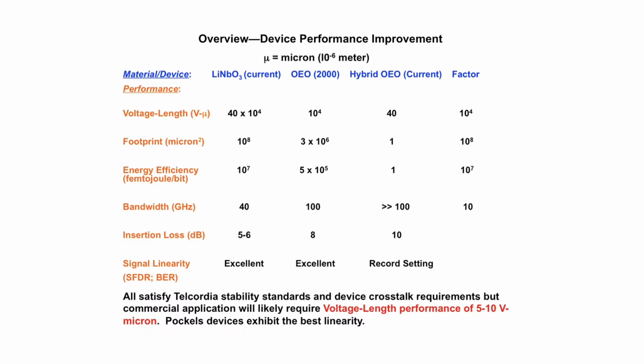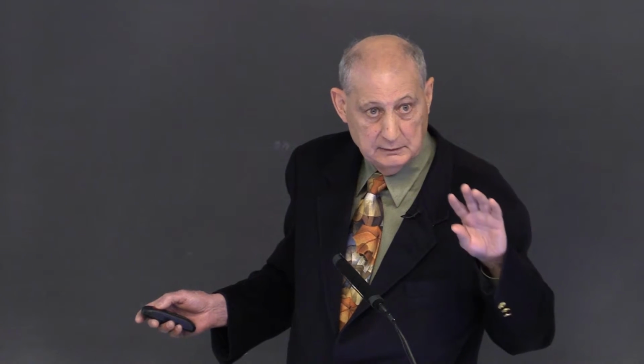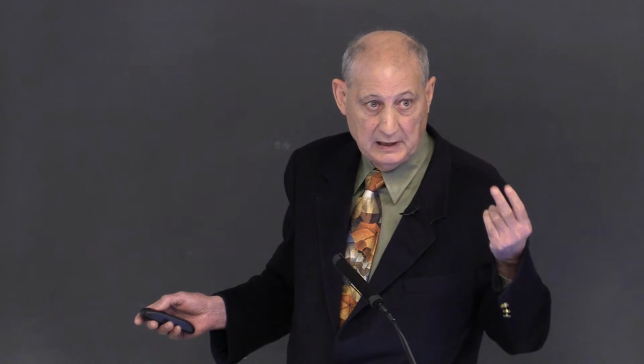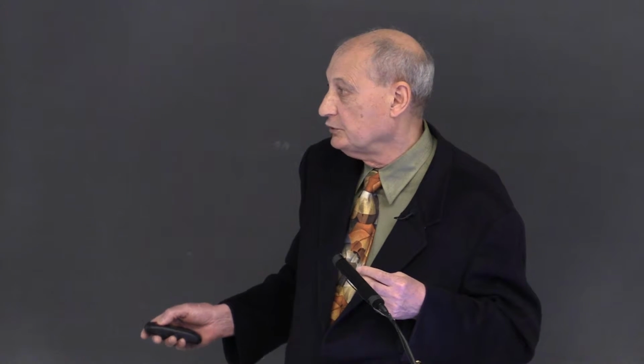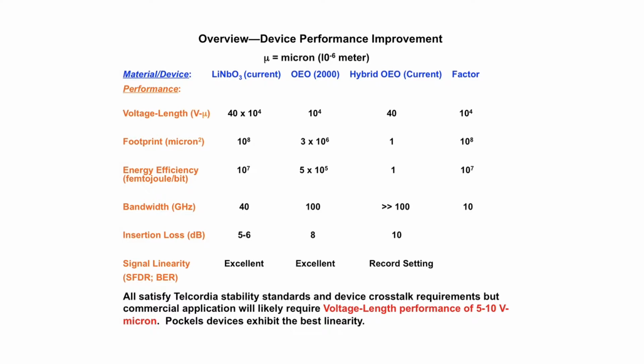Now, all the technologies shown here are Pockels effect modulation. That means when you apply the voltage, the only thing you do is produce a phase change. Electroabsorptive modulators and silicon injection depletion modulators involve both a phase change and absorption. That produces signal distortion. So their signal linearity is very poor. That is, the spur-free dynamic range for analog signals and bit error rate for digital signals is barely usable, but is excellent for all of these Pockels effects.